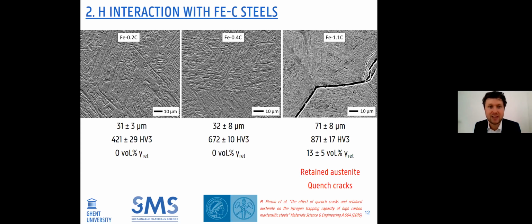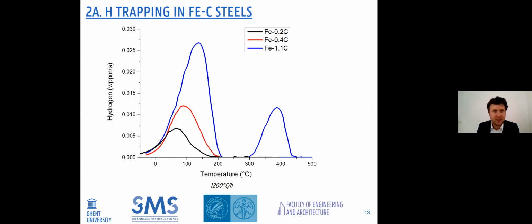So there we tackled this with TDS measurements. TDS was done on the three materials, and here you can see the results. So what do we do? We charge a sample with hydrogen, we bring it to a furnace, we apply a specific heating rate, in this case 1200 degrees C per hour, and we record the hydrogen evolution.